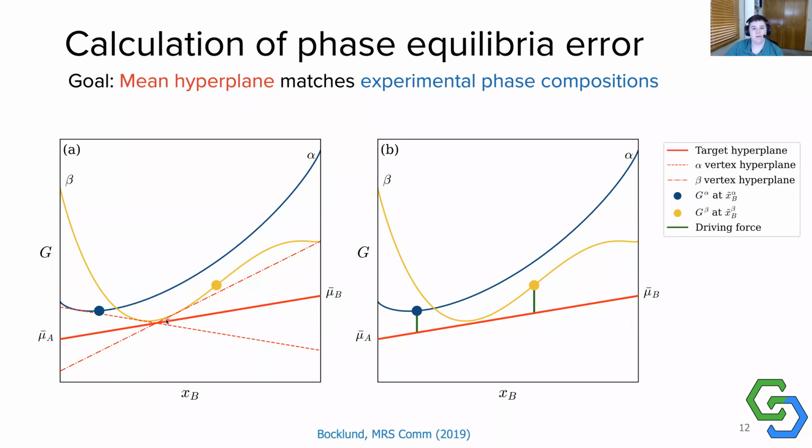For thermochemical data, I think the likelihood functions are kind of obvious in that you are just trying to match some observed value of maybe the enthalpy of formation to the one predicted by your parameters. And so you can just define the likelihood function as the maximum likelihood square difference between the observed and predicted value.